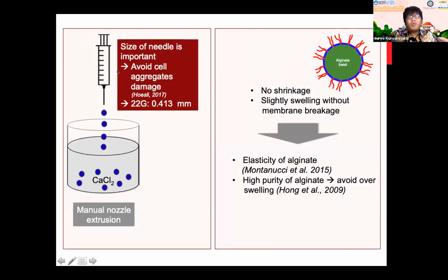For doing the encapsulation, actually it's quite a simple technique. We can just use a nozzle extrusion method by using a syringe with a common needle that is mainly used in hospitals and private clinics. We just fill the syringe with the alginate solution, and then extrude manually. It can be done manually and also automatically with the help of a peristaltic pump, and then extrude the solution into the gelling solution. In this study, we use a calcium chloride solution as the gelling condition.